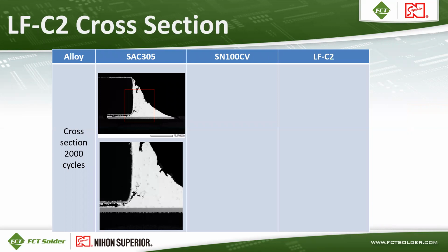Here's cross sections of those solder joints after the 2000 cycles were completed. SAC 305, you can see, has some cracking along the base of the component and from the top of the solder joint coming down. And if that cracking continued, of course, that solder joint would fail and the component would potentially lift off and become a full open.